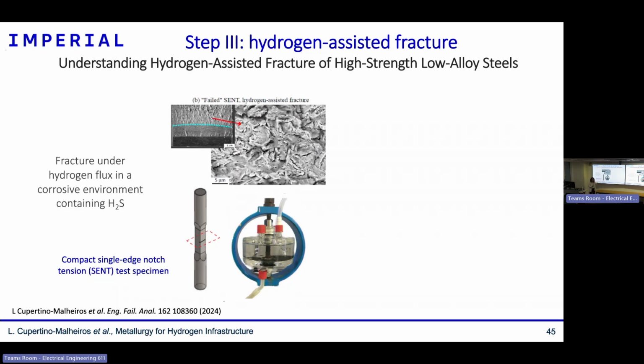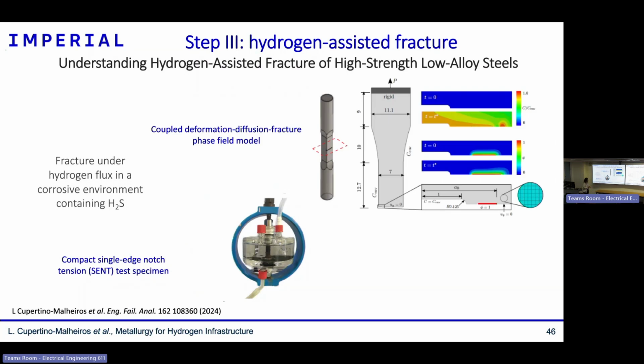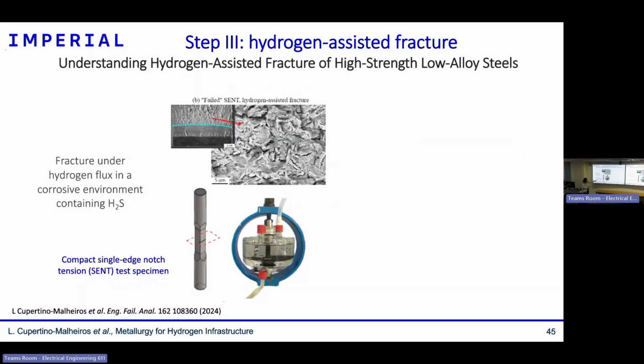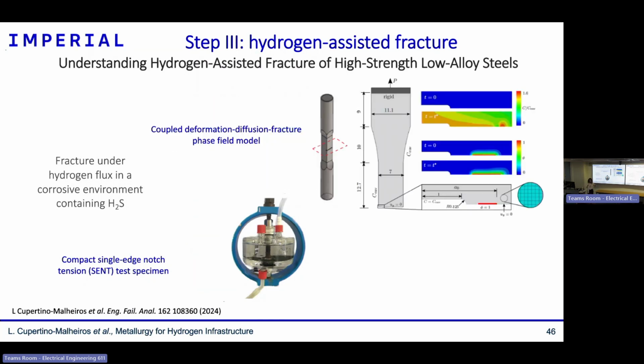And here it's a pass, which means the sample didn't crack; they didn't crack in just 30 days. And that was done with different loads applied to those samples that have a pre-crack. In the samples that cracked, we can see again the same sort of fracture morphology, quasi-cleavage, but here with corrosion products on it. All right, so this is the experimental test, but then we also do the same numerical test to see if we actually get the same thing.